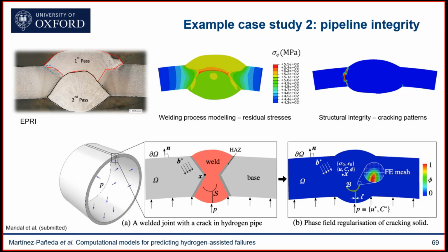And the other aspect of it is that real scale tests are also quite complicated because you have an oxide layer that prevents hydrogen uptake. So you may be running a large scale test that is very expensive and figuring out that nothing is going to happen. And then in practice, after 10 years, you get disruption of this oxide layer, or due to fatigue, you get disruption of this oxide layer, and suddenly you get a structural integrity problem. So we can use the model for that.